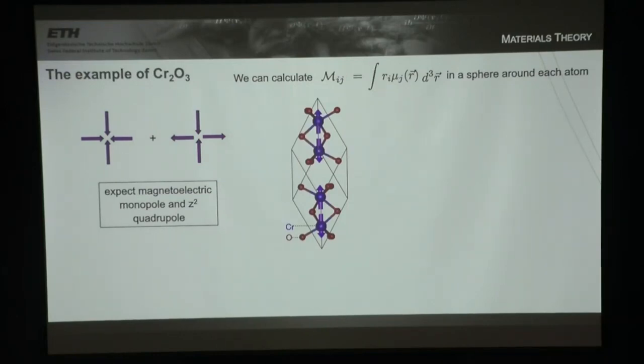So I'm an electronic structure theorist. I do very simple density functional theory calculations. When I do that, I have access to the full electron density, the charge density, and the spin density, the magnetization density. And so I can look around my atoms, and I can calculate R times mu of R in a sphere around each atom. And when we do that, we find indeed we have hedgehogs around each atom, and we have these z-squared quadrupoles. And so what this is telling us is that around the atom, it's not a perfect sphere of magnetization density. If it were, I'd just have a dipole. But I have these higher order multipoles that correspond to the asphericity.